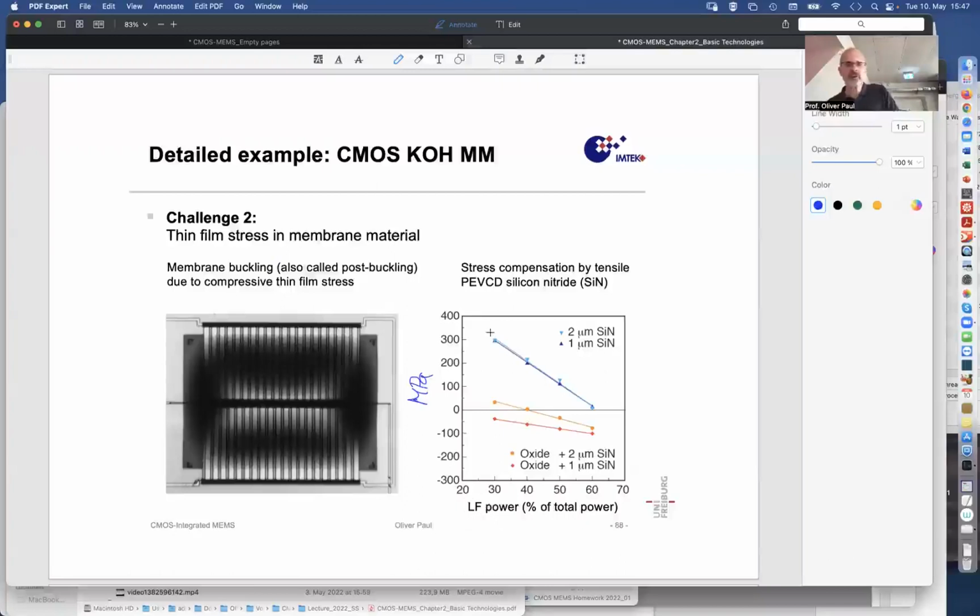And you see that you can reach layers from 300 megapascal to 0 megapascal. This means tensile, strongly tensile. Tensile means pull, and if we continued here, we would go into compressive, but we don't want compressive anyway. So here it's clear that under these conditions, we obtain strongly tensile layers.